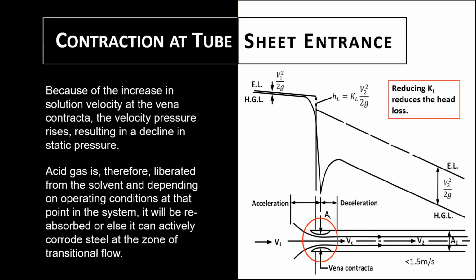Generally, our goal is to maintain tube velocities in the range of 1 to 1.5 meters per second, but at the vena contracta, it's not unusual to have velocities in excess of 2 and even close to 3 meters per second, which can make for accelerated velocities within the tube that are in excess of our general guidelines. Now note that head loss is a function of velocity, the gravitational constant, and a factor K. The intent of a hydraulic engineer is to design a system in which the K value is as low as possible to minimize the effects of entrance conditions on static pressure changes and release of acid gas at this location of the tubes.